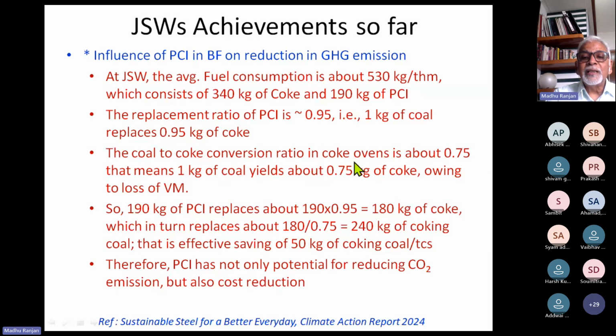So by using these two ratios, if we are using 190 kg of pulverized coal injection, we are effectively reducing coke by 180 kgs, which in turn replaces coking coal of the order of 240 kg. Okay. So by charging 190 kg of PCI, they have reduced by 50 kg the consumption of coking coal. So there is a huge saving of 50 kg of coking coal. They are very expensive, and this saving of coal also has good potential of reducing CO2 emissions from the plant.